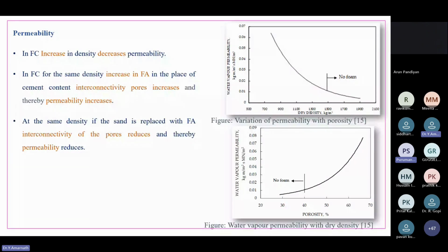A similar thing happens in foam concrete also. In foam concrete, as density increases, permeability decreases. Why? Because as the density increases, if you see here, this is one of the research papers. If you see water vapor permeability, as density is increasing, the permeability is drastically decreasing. Why? Because as density increases, porosity in the concrete reduces, thereby the permeability decreases. This is how it happens in foam concrete.